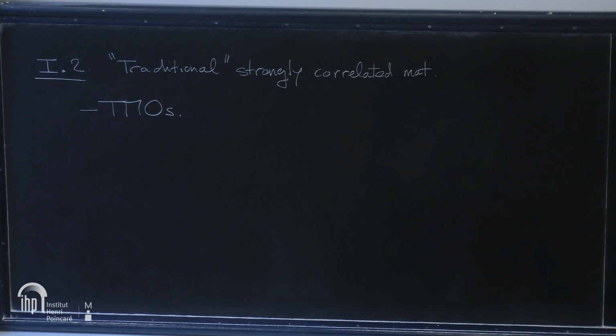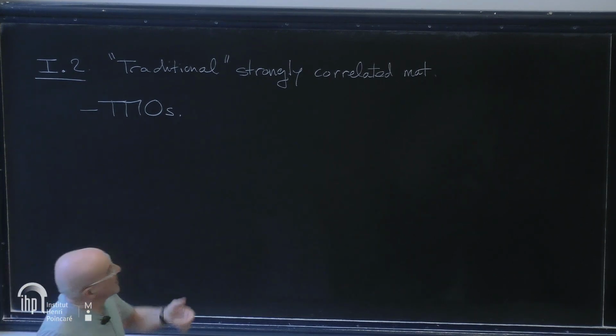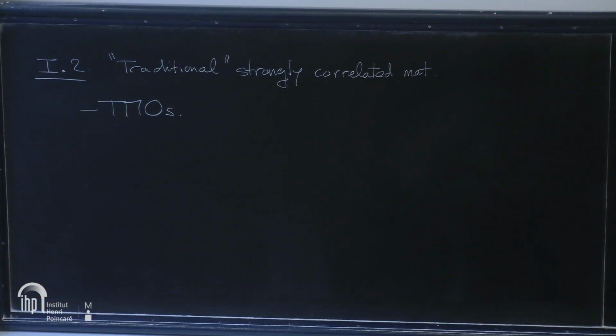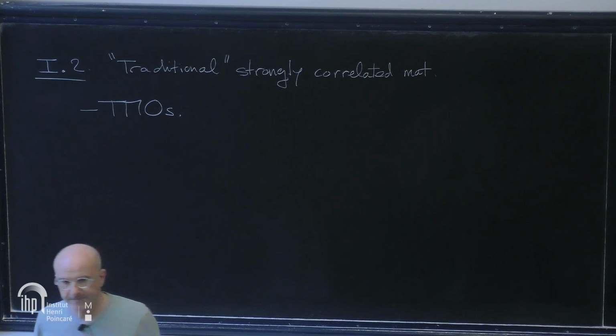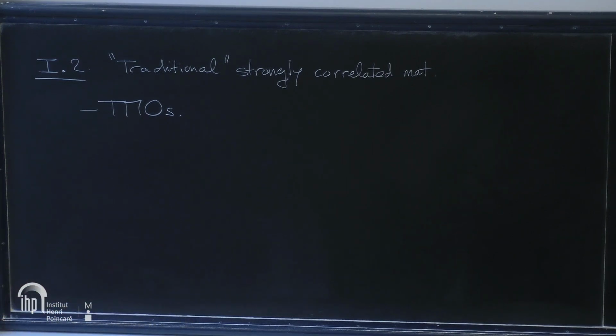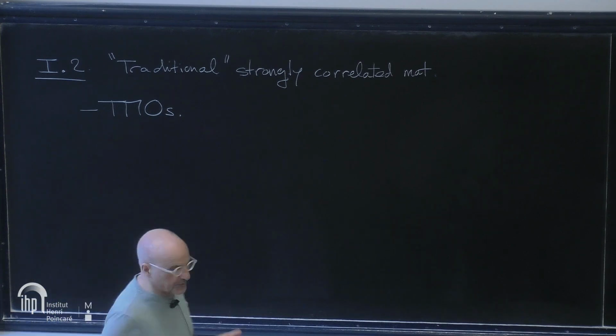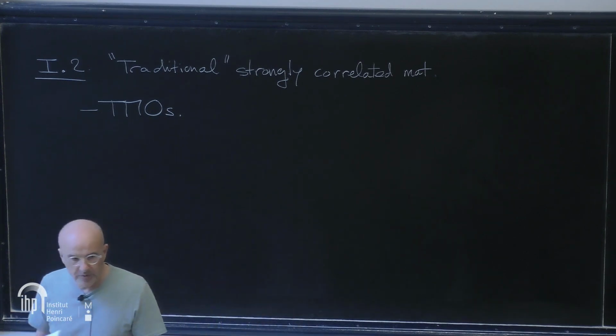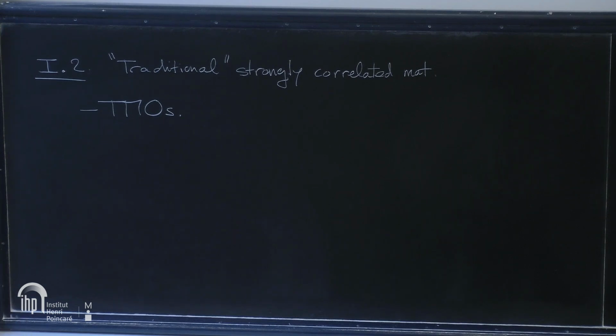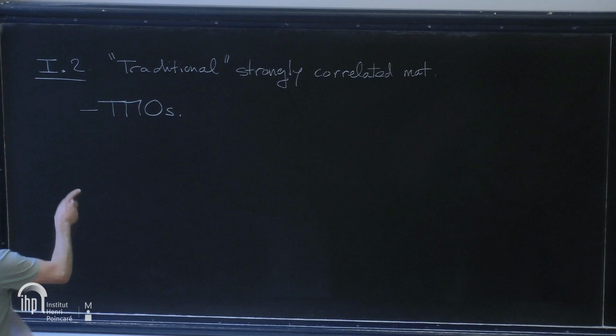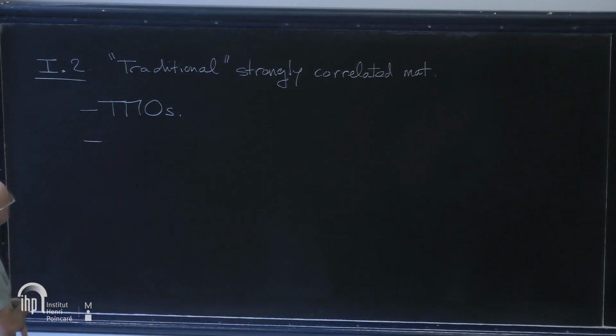And because the bandwidths are typically also of the order of a few electron volts, the ratio U over T can be of order 1 or 5 or something like this. Hence, they fight each other, and we are in the interesting regime where electrons are not completely localized and also not completely itinerant, which is the regime where strong correlations are manifest. But the price to pay is that the actual value of U is not known so precisely. It requires complicated full first principle calculations of the screening phenomenon to be able to estimate the value of this parameter. Okay, so that's a traditional platform for strongly correlated materials.